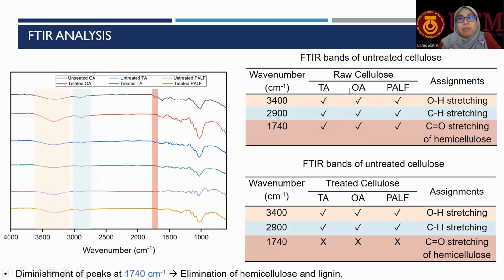So here you see that for raw cellulose, all the peaks are visible, but the peaks for hemicellulose and lignin at 1740, which is here, have diminished. For example, for untreated OA, you have this peak. For the treated OA, this peak no longer exists. For treated TA, you can see this peak for lignin and hemicellulose no longer exists. For untreated PALF, which is indicated in purple, we can see the peak here, but the peak for the treated PALF no longer exists.